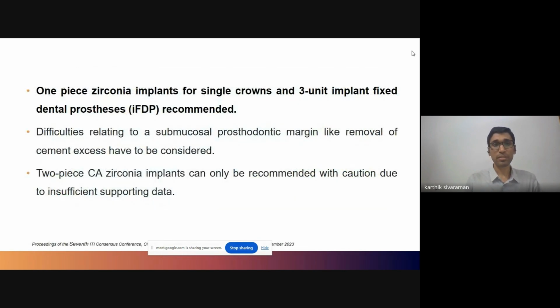And what were the recommendations? The recommendation of the ITI body was that one-piece zirconia implants be used for single crowns and 3-unit implant fixed dental prostheses only. So they did not recommend any versatile or diverse applications of zirconia. They have recommended that the two-piece commercially available zirconia implants be used with caution since there is insufficient supporting data, and the one-piece zirconia implants be used only for single crowns and 3-unit implant fixed dental prostheses.